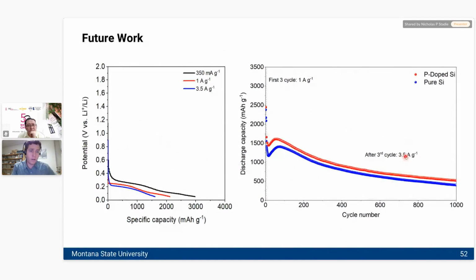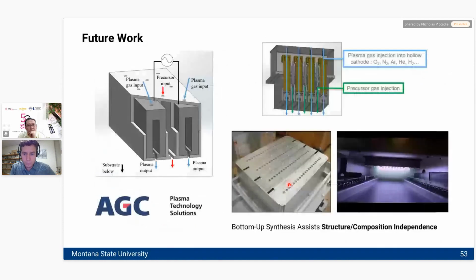We're now looking at even higher rates of like 6 amps per gram, which is on the order of about a 20-minute charge time. Very, very fast charge times. Graphite doesn't love to be charged that fast, and so graphite takes a little bit longer.